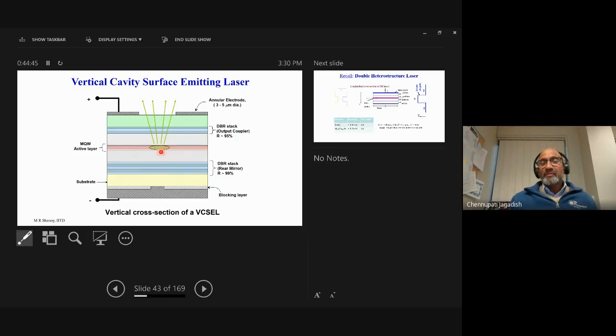And then you put some multi-quantum wells here, and then another distributed Bragg reflector, but you keep the reflectivity of this Bragg mirror a bit lower than this one, so that light comes out in the vertical direction. Again, you create a p-n junction and inject current, and then look at the light coming out. In this case, this aperture will determine the shape of the laser mode, and typically you end up getting a beautiful circular mode.